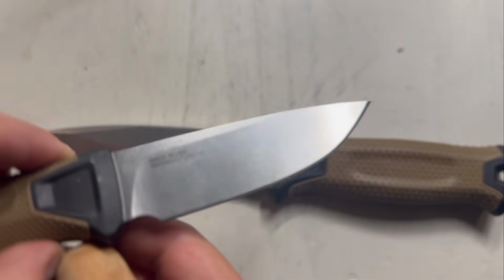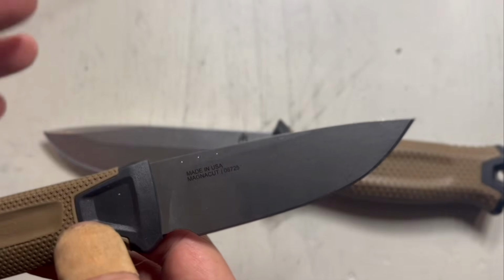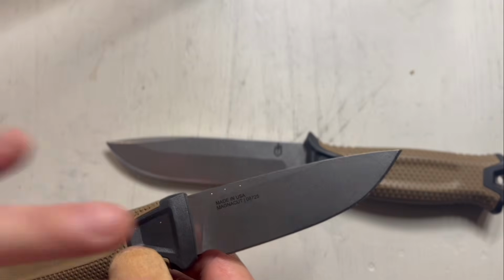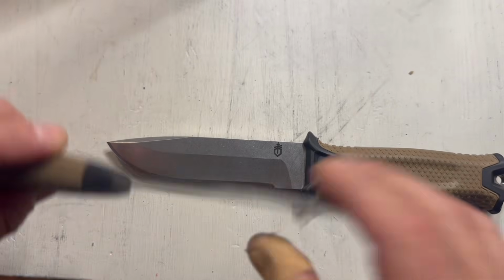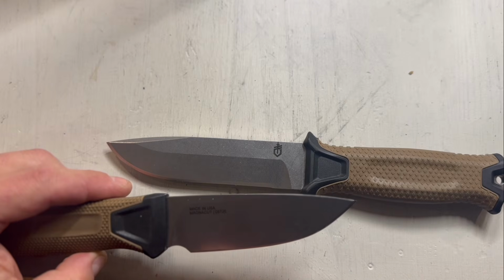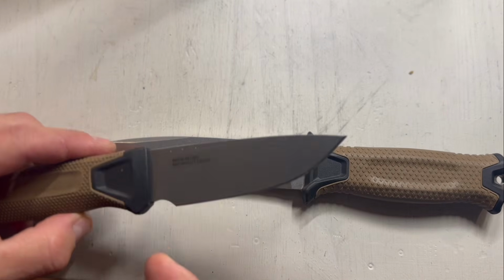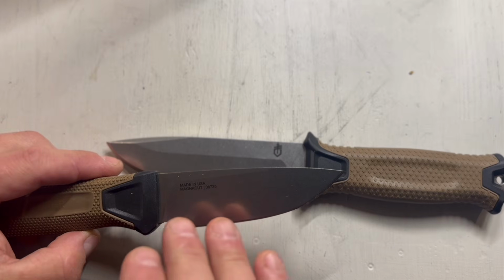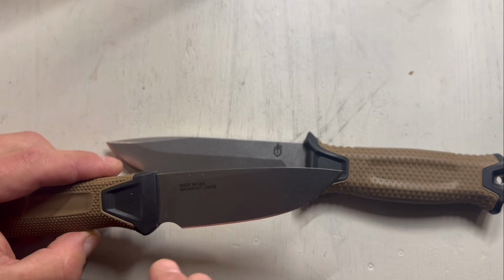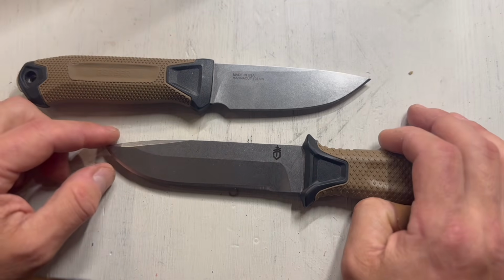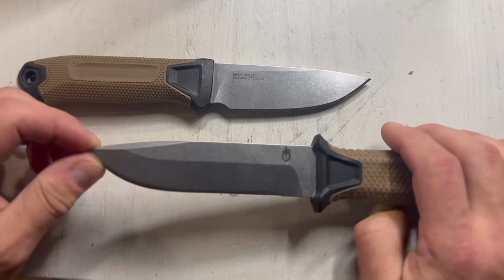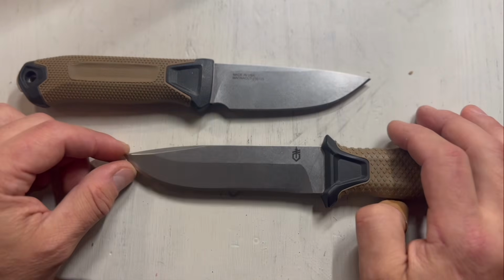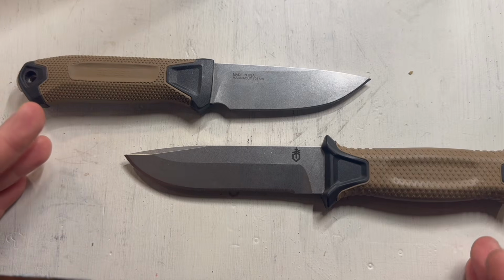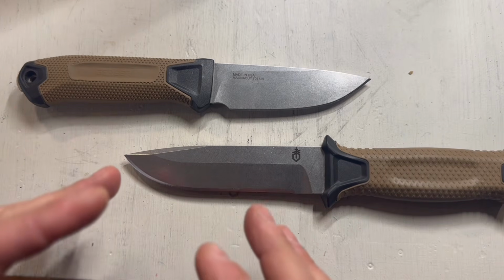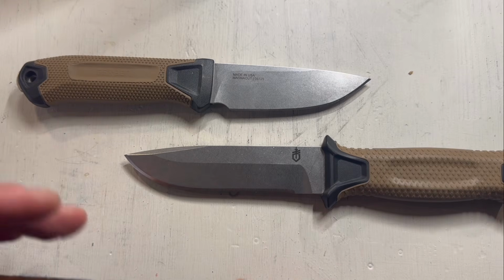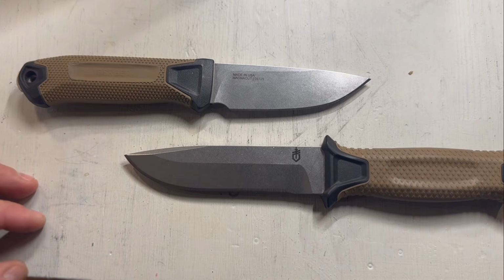This steel is called CPM MagnaCut. MagnaCut is all about reaching this balance between corrosion resistance, edge retention, and toughness or resistance to strain. And this steel is amazing in the sense that it allows flexibility. So if you heat treat it a little bit lower, just over 60 to 62 HRC, you will get max corrosion resistance. If you heat treat it above 64 HRC, you will get max edge retention. But if you heat treat it somewhere between 62 and 64 HRC, you will get this balance point where you're getting a really decent performance in all three areas. That's why I did the test.